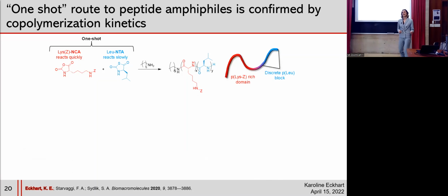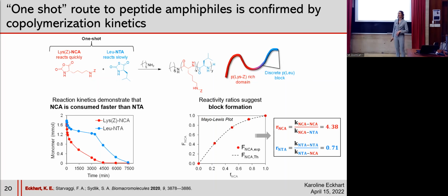So we wanted to use this one-shot synthesis to create a functional peptide amphiphile. So we selected lysine as the hydrophilic block on the NCA and leucine as the hydrophobic block on the NTA. And we polymerized these and studied the copolymerization kinetics to identify if it was actually forming a block. And what we can see here is that in the beginning of the polymerization, we get rapid consumption of the NCA monomer, adding on that hydrophilic block. We are still getting some consumption of the NTA during that first phase. And then when the NCA is fully consumed, we get polymerization and propagation of the NTA to form a gradient copolypeptide.